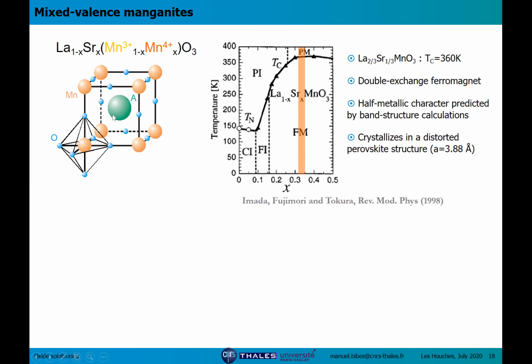By varying the relative ratio of lanthanum and strontium, you can change the valence of manganese from 3+ to 4+. This phase diagram shows you the properties of these lanthanum strontium manganite compounds as a function of doping. Lanthanum manganite at zero doping is an antiferromagnetic insulator. As you introduce strontium, you establish double exchange, and so the material becomes ferromagnetic and metallic, and reaches a maximum TC of about 360 K for doping levels around 0.3, 0.4.